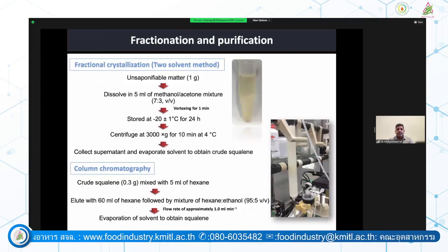After extraction, I passed this through simple fractional crystallization, storing it at -20 for 24 hours, so that most of the wax materials could separate. Squalene is not crystallized, because squalene has 6 unsaturated double bonds. It stays liquid even at -40 degrees centigrade. Further, with column chromatography, with just one run of hexane, we can easily separate the squalene with the highest purity.